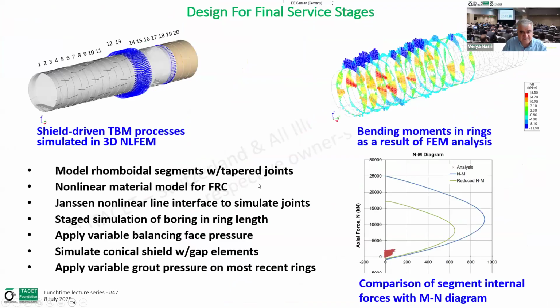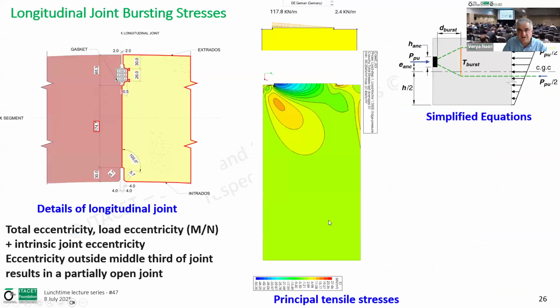Now, that's the best practice with tapered joints. And we need to consider a nonlinear constitutive model for FRC. We use Janssen nonlinear line interface for the joint. We use sequential excavation modeling, and we apply face pressure and its variability. We consider the conical shape of the shield using gap element, and then we use the grout pressure considering the age of it and the strength of it.